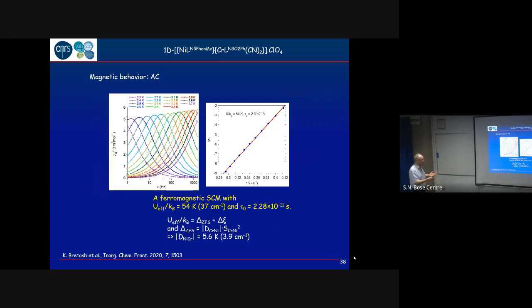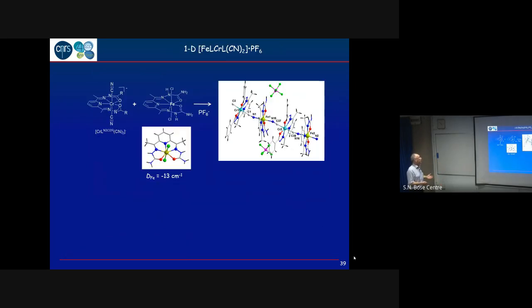Okay, so for this system, of course, we have the expected AC susceptibility data. So you recognize now the plots I have shown before, and we have a single chain magnet with an energy barrier of 54, just a number. So this is for nickel. So we can do better if we increase the spin of the nickel center. So we can move from nickel to iron. And, of course, we did.